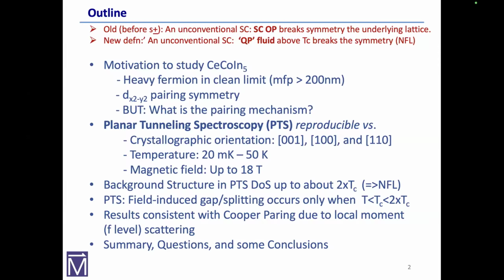It's a non-Fermi liquid where the transport, optical and thermodynamic properties aren't just determined by how the carriers sit in the lattice. So I'll start with a quick motivation why we study cerium cobalt indium 5. I think most of you are better experts than I am. It's a great superconductor. Because of a lot of the people with Joe Thompson, you learn to grow very, very clean materials with a very long mean free path. We showed a few years ago, and there's been agreement ever since, it's dx squared minus y squared pairing symmetry. But I remind you that pairing symmetry doesn't give you pairing mechanism and vice versa. So there's still a discussion of what the pairing mechanism is.